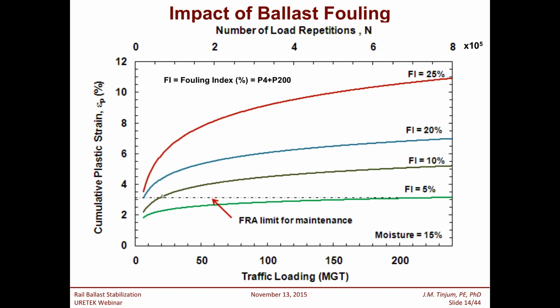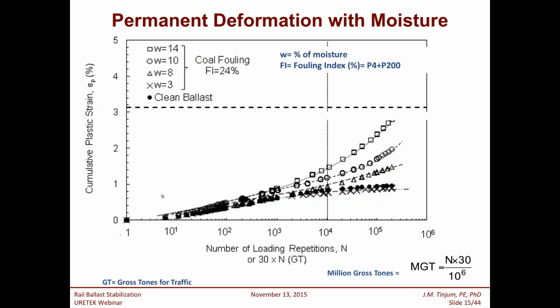What is the impact of ballast fouling? Well, this is an example of a graph where we place fines in a clean ballast, and fines are defined by the percentage passing the number 4 sieve plus the percentage passing the number 200 sieve. That is called the fouling index, and you'll see the highly fouled ballast deteriorates much more quickly, exponentially, than a cleaner ballast. In this graph you see the moisture was controlled at 15%. So as we increase the fines, the rate of cumulative plastic strain accumulation increases. This graph that we're looking at now shows the impact of increasing the moisture content. In this particular graph, we have coal dust fouling at a FI equals 24%.